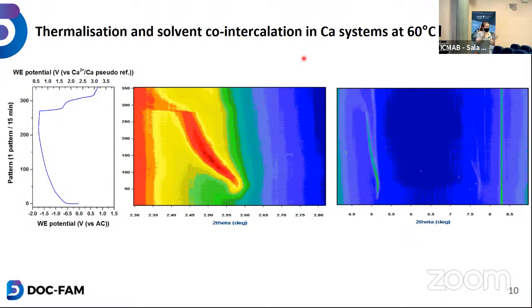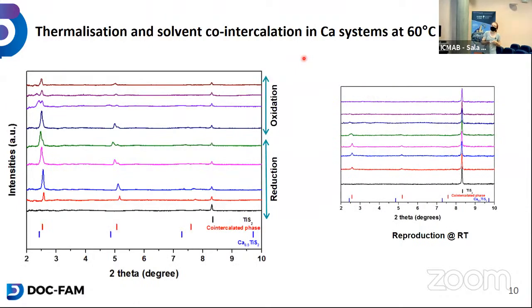So let's have a closer look at the patterns. And you can see that at the early stage of the reduction, the first thing you see is a co-intercalation, but as you go a bit further, you will have a second peak here. Here the peaks are merged a bit, it's more clear here.